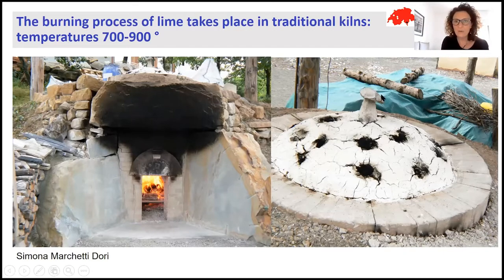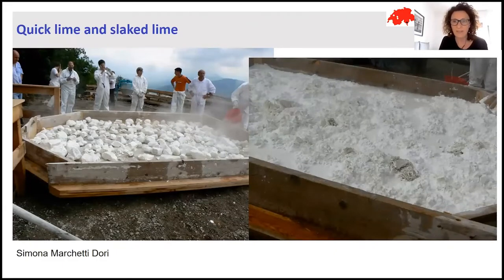When the last stone is completely burned, it means that the process is ended, and then we can stop the firing process and extract the material. The material that comes out after the burning is the quicklime, so the calcium oxide, that needs to be slaked, so mixed with water, in excess of water.